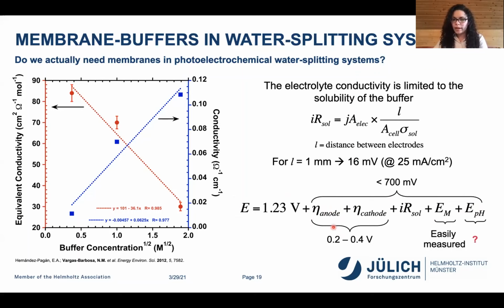And so if we look at the literature, typical overpotentials for anode and cathode in buffered systems are between 200 and 400 millivolts. And so we already have about 10 or 15 here if we are at very high concentrations and very small distances. So that means we're definitely going to need a membrane, which we can measure. And then the question was, what is this pH thing doing, and is it a problem?